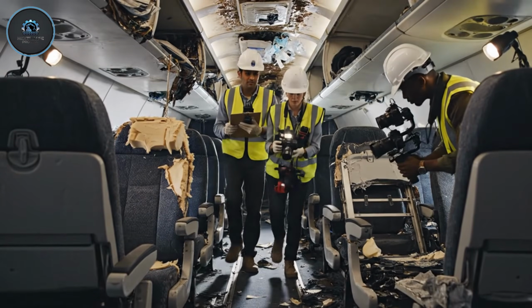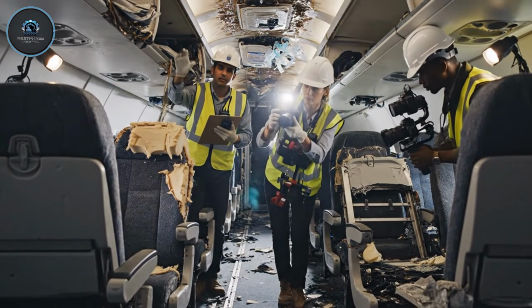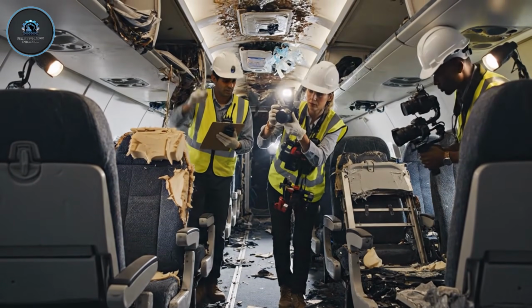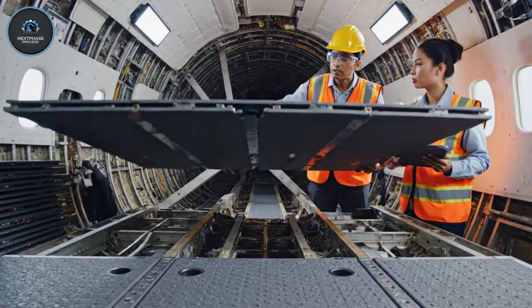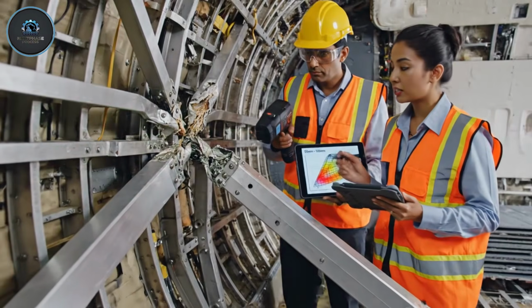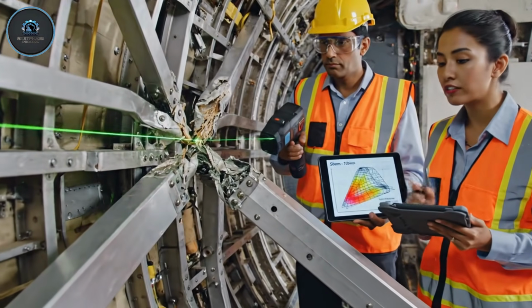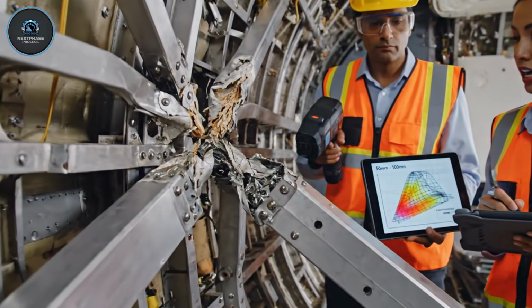Documenting the failure mode on the left side. Bolts sheared cleanly here, while the seat across the aisle remains intact. Note the water staining. Look at the deformation on the S4 stringer. The laser scan confirms it. We have 50 to 100 millimeters deviation right here.